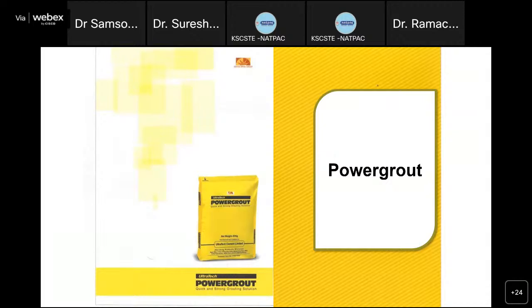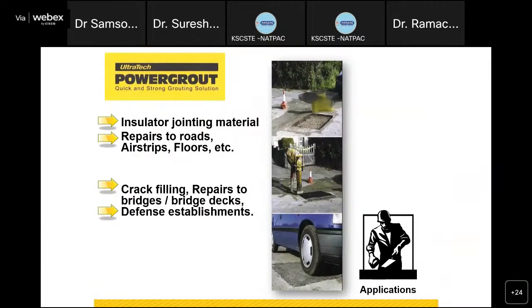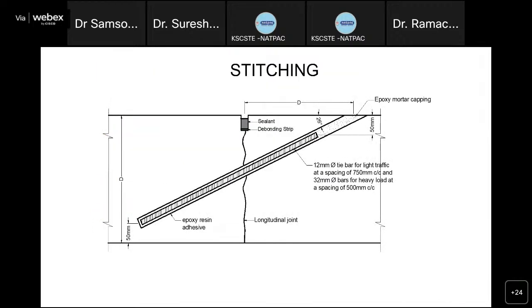There are a lot of materials. One of them, of course, is the UltraTech Powergrout, which gets a strength of about 40 MPa in 24 hours. There are several such grouts available in the market, and this has been quite popular in Mumbai for several roads. This has been used as a solution. The advantage with this grout is that it is an excellent material for repairing roads, airstrips, and floors, and for crack filling, repairs to bridges and bridge decks also. Very fast, it can be open to traffic.